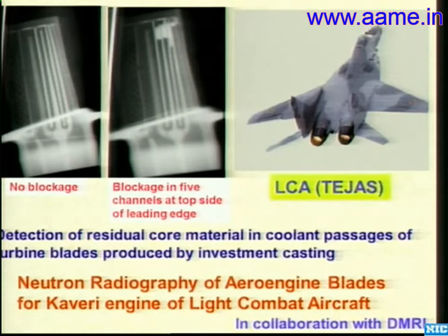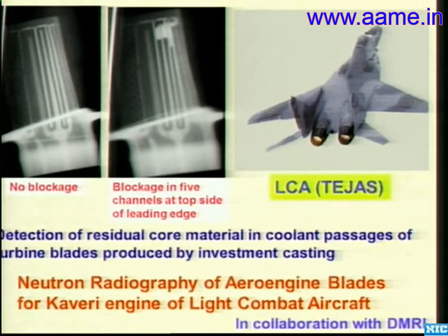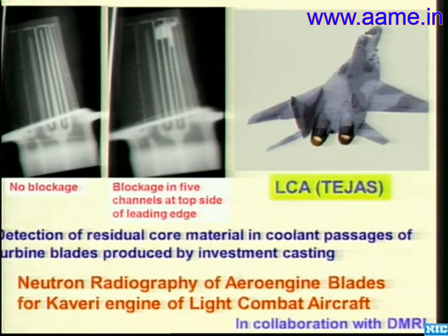For the Light Combat Aircraft, internally cooled blade development was taken up at DMRL. A well-made blade has the ceramic core completely leached out, whereas a defective blade retains residual ceramic core, which creates a hot spot during engine operation and causes premature failure. As part of the blade development program, neutron radiography-based inspection was developed. Conventional X-ray has very low sensitivity for detecting ceramic core inside nickel-based alloy because the alloy absorbs X-rays far more than the ceramic, giving insufficient contrast. Neutrons provide much higher contrast since ceramic absorbs neutrons strongly relative to nickel-based alloys, enabling qualification of blades to confirm no residual core remains.